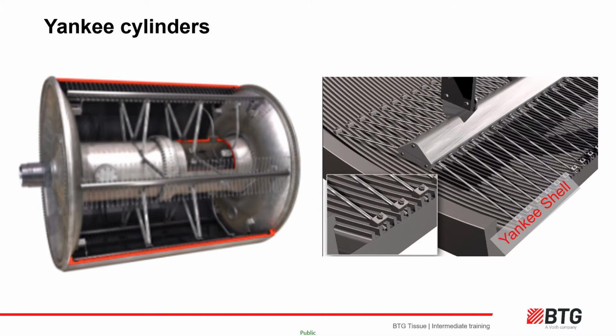So steam is fed into the Yankee cylinder anywhere between 4 and 12 bar pending the design. It condenses and the resultant heat transfer heats the shell, which then dries the sheet. Condensate must be evacuated from the cylinder at the same rate as it forms to prevent waterlogging and to maintain an even MD and CD temperature on the shell. The inside of the Yankee shell is ribbed or grooved in the MD direction.